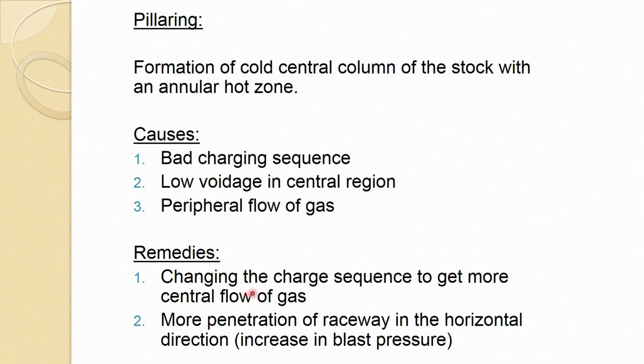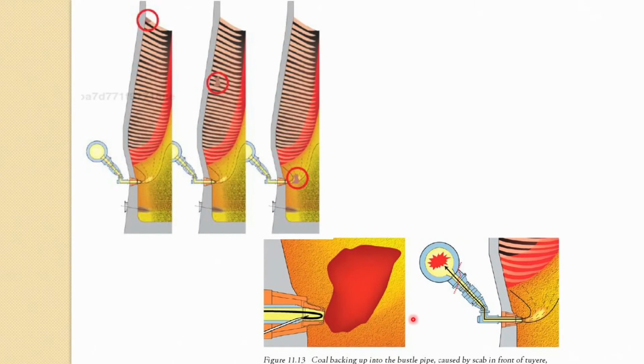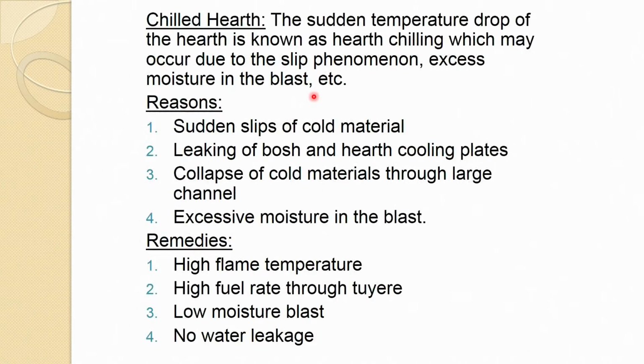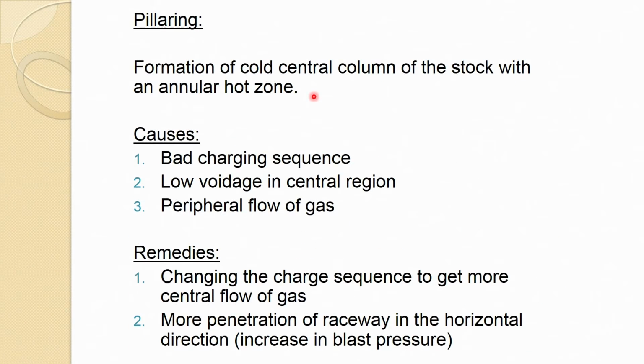So, remedies: change the charge sequence to get more central flow of gas, more penetration of raceway in the horizontal direction. That is, increase in blast pressure. When you increase the blast pressure, the raceway penetration will increase more in the horizontal direction, which will promote the central gas flow. That will help in better heat transfer and mass transfer. So, that may not occur, and it is one of the reasons of hearth chilling, because when that mass becomes very high, suddenly it can collapse into the hearth and hearth chilling may occur.